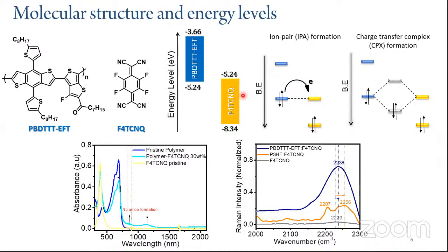And the basic mechanism of doping includes two ways. One is the ion pair formation, that is electron transfer from the HOMO to the LUMO of the dopant. Whereas one more mechanism is possible in other cases, that is the charge transfer complex formation, where the frontier molecular orbitals of the polymer and the dopant hybridize to form a new set of orbitals, that is occupied as well as empty orbitals.